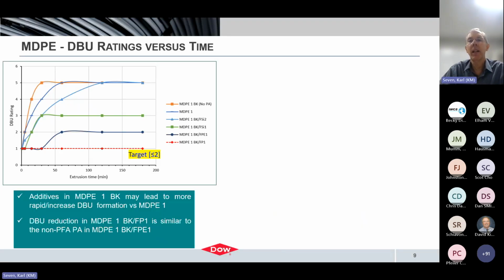So this graph here on the left is basically capturing the die buildup performance over time over the entire 3-hour test period. I'll point out a couple things here. Comparing the die buildup of the base resin MDPE1 to the fully formulated MDPE compound, which of course has no processing aid, indicates that the additives in the fully formulated compound did contribute to increasing the rate of the buildup. And so those additives increase the rate of the buildup, either by forming it or the additives themselves contributed to the buildup. The traditional fluoropolymer, of course, showed very good performance, and also the polar polymer additive showed good performance in comparison to that.